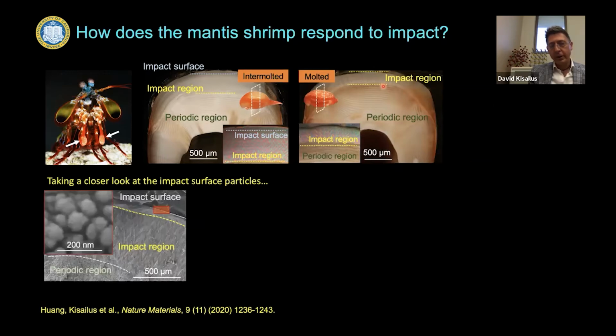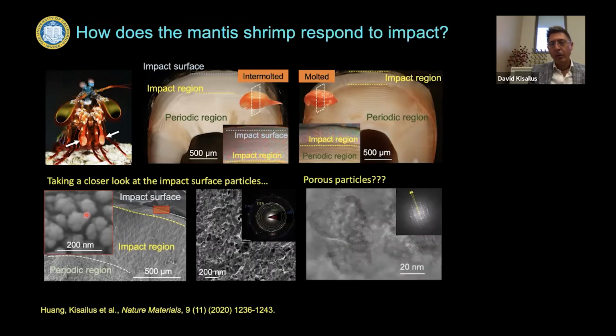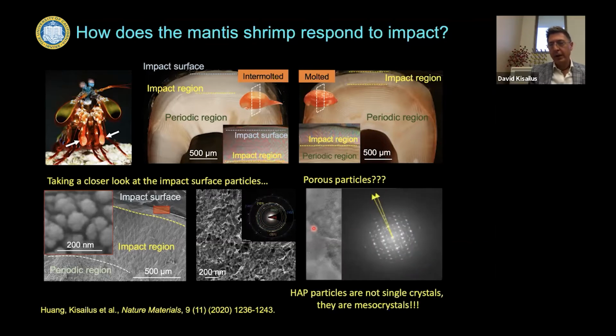But we took a closer look at these nanoparticles. And again, in SEM, they look like raspberries, if you will, aggregated particles. But when we took a closer look in TEM, what we thought were single crystal particles looked kind of porous. And the electron diffraction patterns that we subsequently used here showed that they're not single crystal, but you can actually see arcs in these patterns, indicating that they're mesocrystalline particles. And so we've done some additional TEM analysis of these particles.